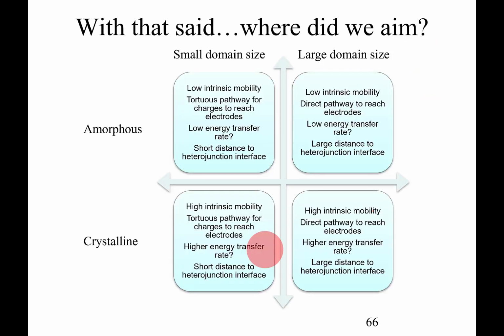So again, we aimed down here with our samples, but we actually wonder now if, because maybe this crystallinity is bad for energy transfer because of the fluorescence issue, because of aggregation and problems with that, maybe we actually want to have smaller domain size and we want to have a more amorphous sample. Again, very complicated system despite being such a simple molecule.